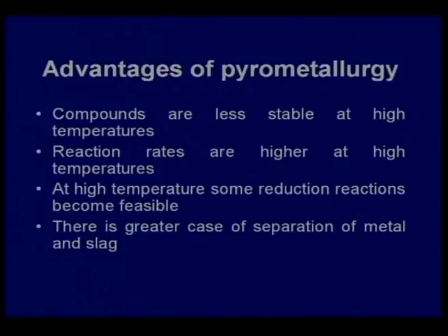Take a simple example of, say, decomposition of calcium carbonate. Calcium carbonate on heating decomposes to calcium oxide and CO2. Now, in theory, as you keep increasing the temperature, the partial pressure of CO2 increases. So, it is not that it suddenly decomposes, like you should know for water.